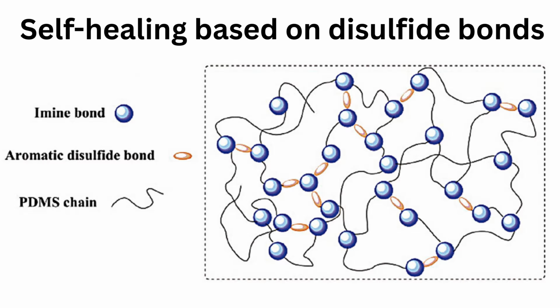While polyurethane materials incorporating disulfide bonds can demonstrate self-healing capabilities, this modification typically compromises their mechanical performance. Such trade-offs between self-healing ability and structural integrity have significantly constrained the practical applications of these materials. Furthermore, the commercial viability of these systems is limited by the high cost of aromatic disulfide monomers and the challenges associated with their industrial-scale synthesis.